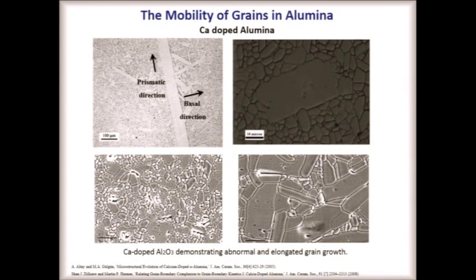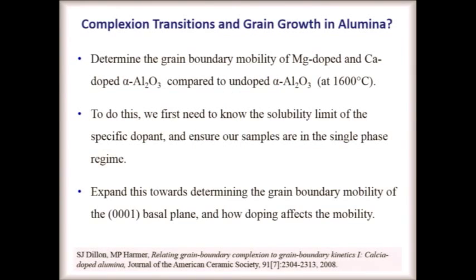Just to reinforce the driving force, so this is from Mehmet Gulgun, was, I think, way over the solubility limit in these samples. But it doesn't matter because the phenomenon is still there. You get these elongated grains of alumina, which these big platelets are parallel to the basal plane of alumina. But you can see this also for smaller grain sizes. Silicon tends to make it equiaxed and abnormally large.